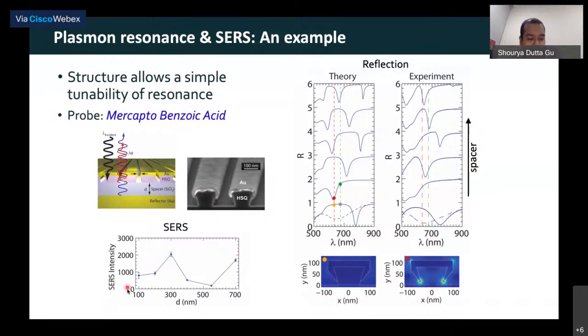Okay. And correspondingly, if we measure the Raman from this molecule, mercaptobenzoic acid, we see that, look, for certain values of D, like for example, here 300 nanometers and 700 nanometers, the SERS intensity or the Raman intensity is very high. However, for some other values, like for 100 and for 500, the values are very low. Okay. So what I'm trying to emphasize here is that by choosing the structure properly, we're either able to enhance the Raman or completely suppress the Raman signal that we are getting.